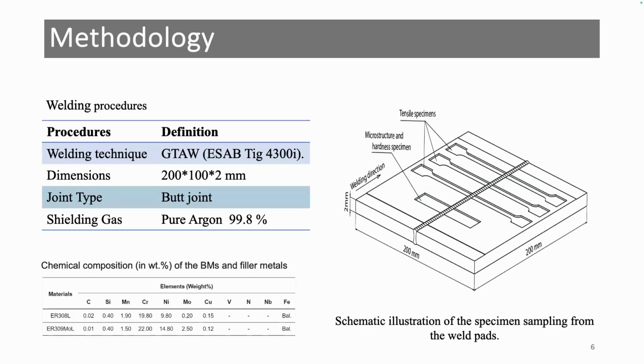For the methodology, we use the GTAW technique. The dimensions of the plates were 200 millimeters by 100 millimeters, and the thickness was 2 millimeters. Joint type was butt joint, and the shielding gas was pure argon. Then we took specimens for microstructure, hardness, and tension tests. Furthermore, we use two different filler metals. The filler with molybdenum was used for welding the low carbon steel with the manganese steel in order to give some chance for carbide precipitates at the fusion zone, and then we can increase the joint efficiency.